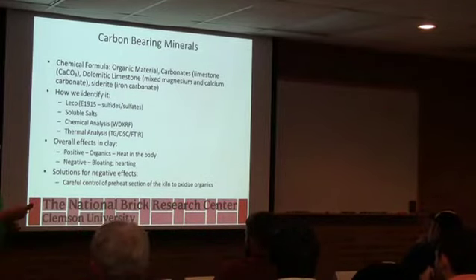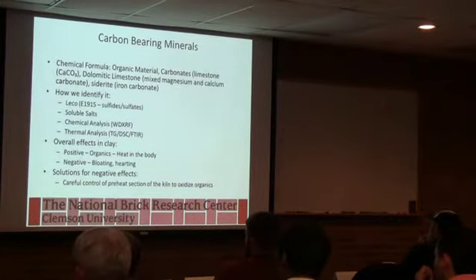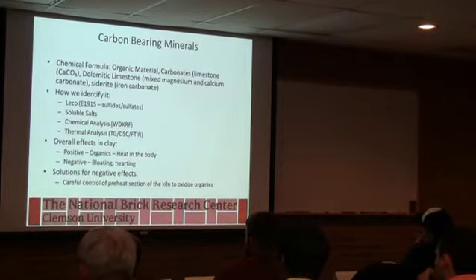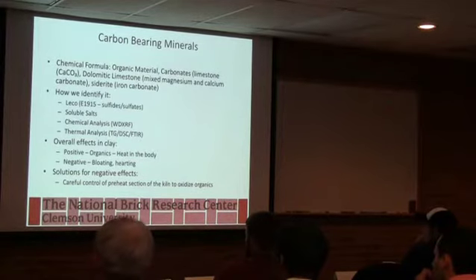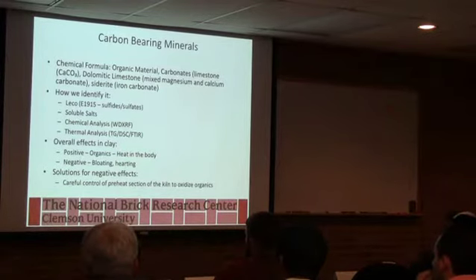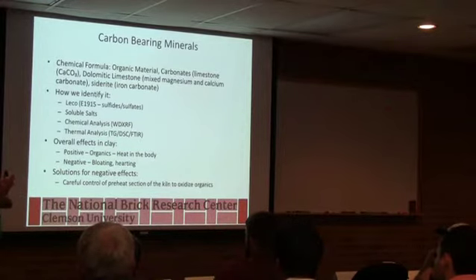And I used to work on Bennett's material. It was real easy for that material to bloat because it actually had limestone. And the temperature limestone decomposes varies by how much carbon dioxide there is in the kiln atmosphere. And so if the kiln was running sort of reducing, the temperature for the decomposition got higher and higher while the glass formation temperature is going lower and lower. And if you got them too far out of sync, you sealed the surface and all that carbon was trapped. So that's a pretty neat example of bloating there.